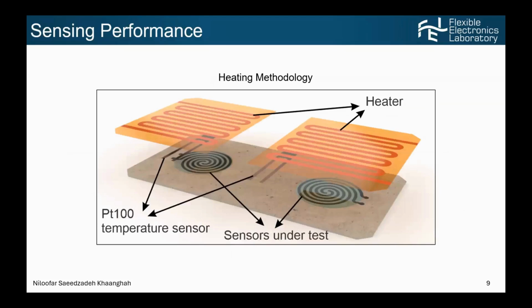To test the sensing performance, as we know, one of the common ways is putting the sensor on top of a hot plate and then using a microcontroller, then doing the cycling. But here I use a different heating methodology. As you see in the picture, I use a heater which is a silver printed serpentine pattern on a Kapton layer. And I applied this heater right on top of the sensor. We applied voltage to this heater and received heating in return. I also used a commercial PT100 sensor to monitor the temperature. Also, this setup had a LabVIEW program and a digital multimeter to monitor the signal.